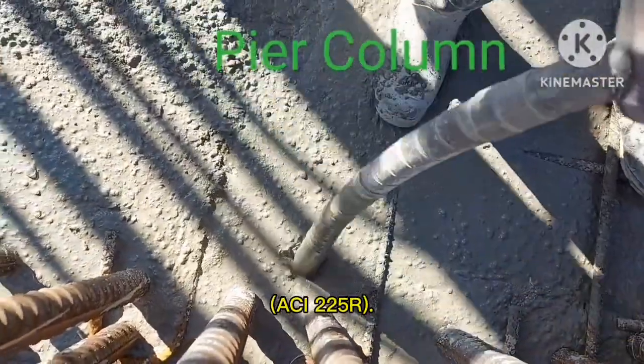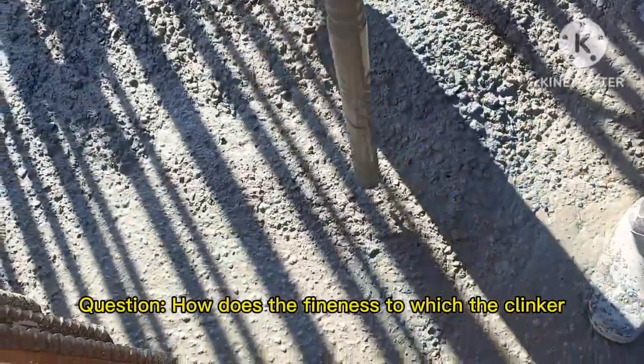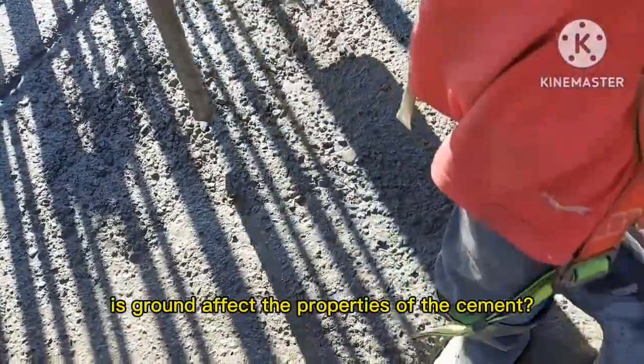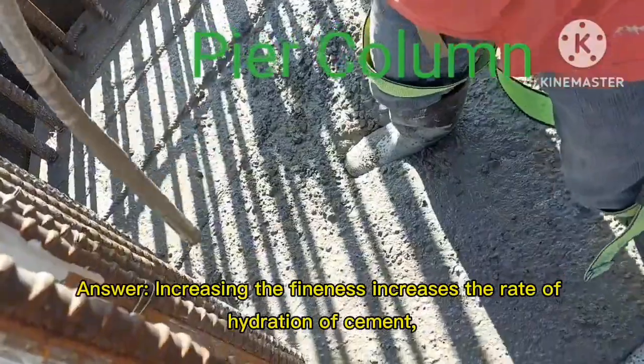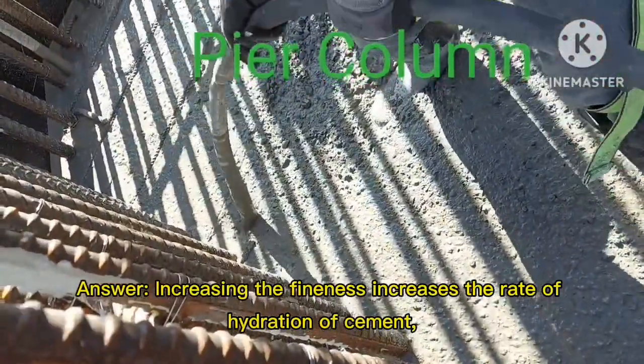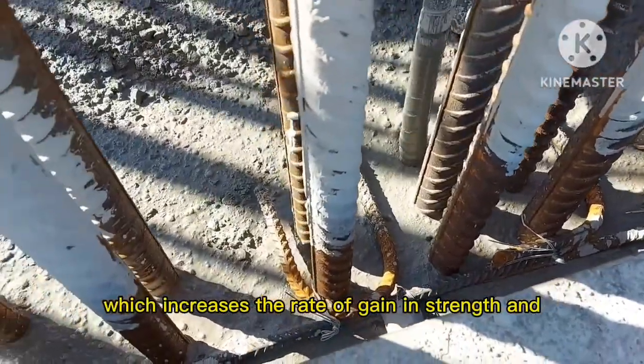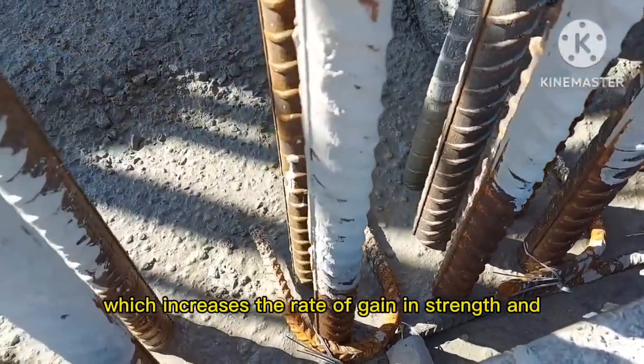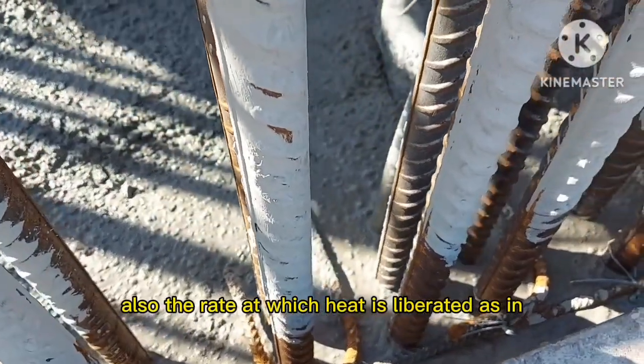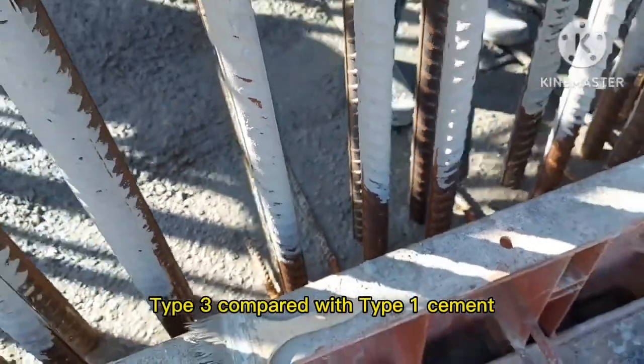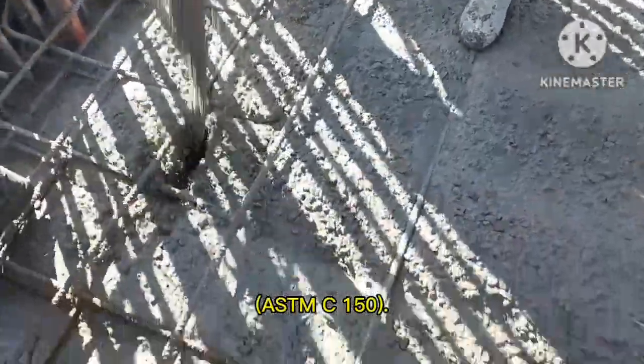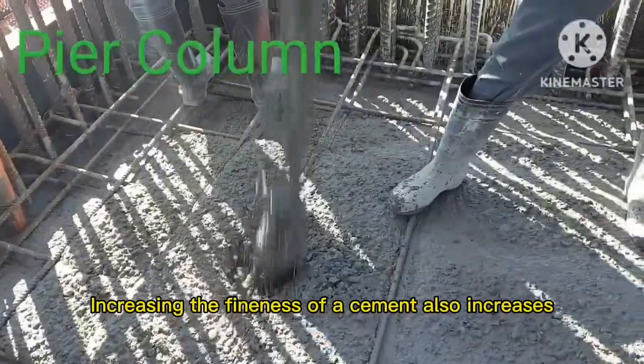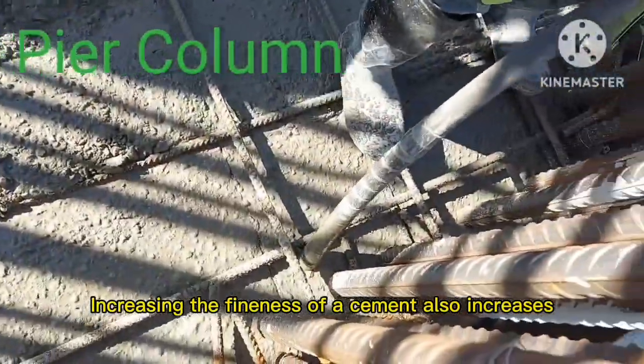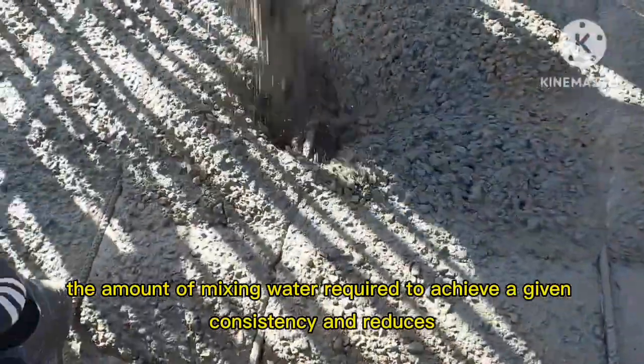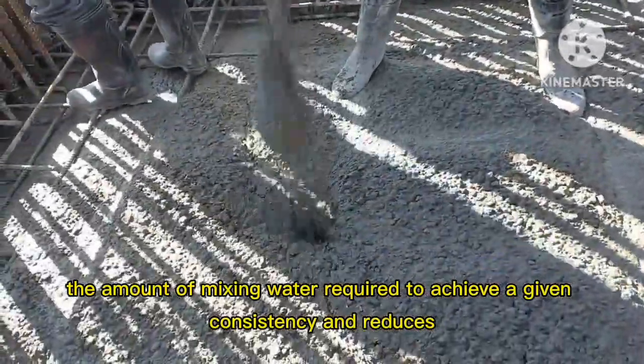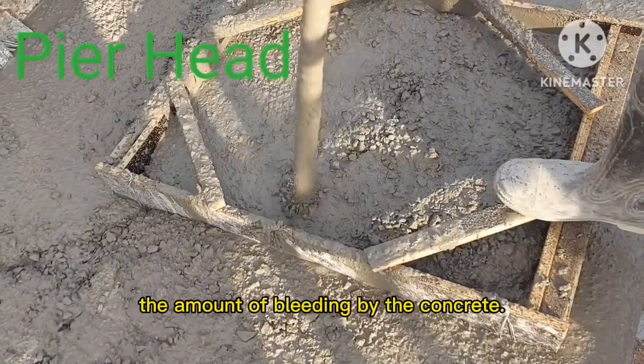cement, ACI 225R. Question: how does the fineness to which the clinker is ground affect the properties of the cement? Answer: increasing the fineness increases the rate of hydration of cement, which increases the rate of gain in strength and also the rate at which heat is liberated, as in Type III compared with Type I cement, ASTM C150. Increasing the fineness of a cement also increases the amount of mixing water required to achieve a given consistency and reduces the amount of bleeding by the concrete.